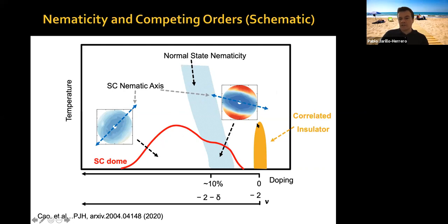Well, no, it's not fixed to some external strain, because strain would not depend on the density of the electrons in your system. There may be strain locally, the fact that you see an ellipse here or here. If the system was truly spontaneously choosing a particular angle, if there was nothing pinning that ellipse, you would not really be seeing the ellipse. You would be carrying the rotation of the ellipse with you, so to speak, because if all angles are exactly identical in the system, with your parallel field you would be sort of dragging the ellipse along.